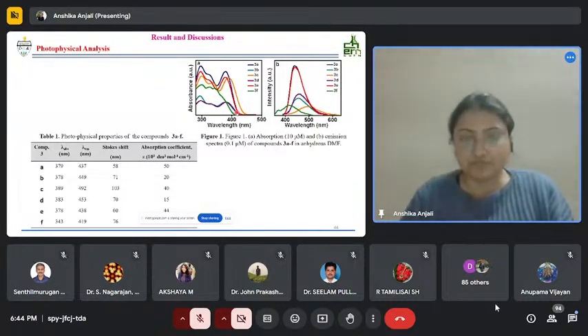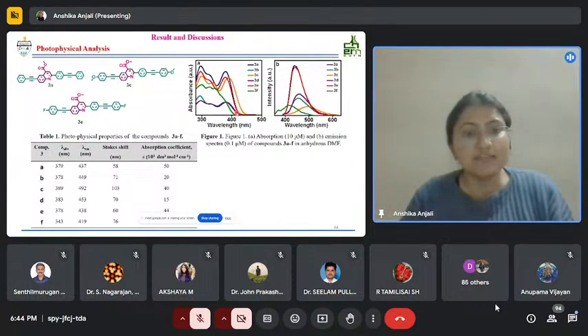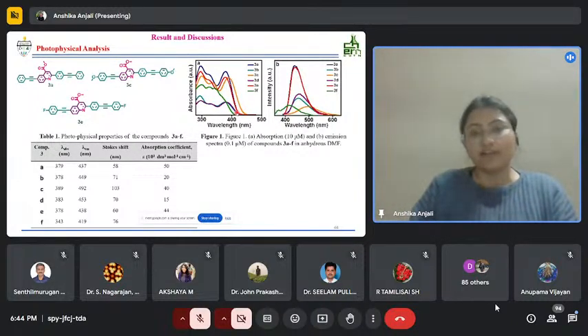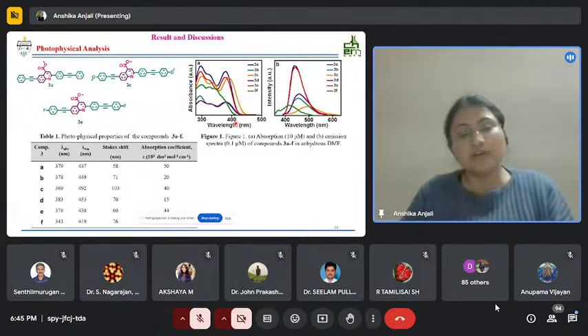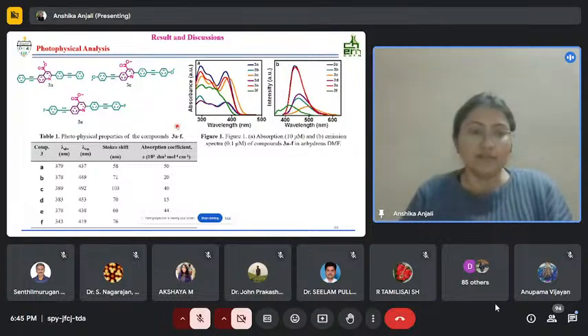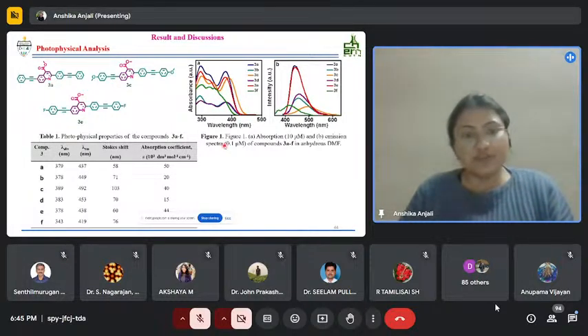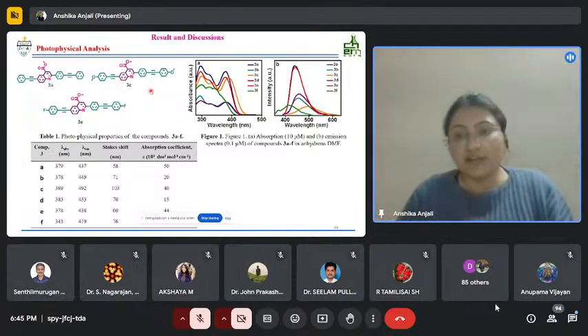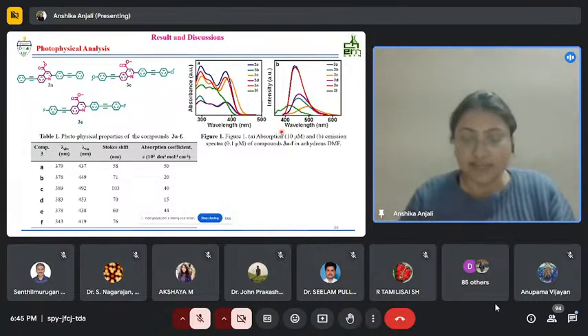So here compound 3A with the phenyl as end caps, then compound 3C with 4-methoxyphenyl as end caps, and compound 3E with 4-fluorophenyl as end caps resulted in higher ICT effect. So when we are comparing these compounds with the previous set of molecules with only one pi linker, they did exhibit a red shift, which might be because of the extended conjugation with additional phenyl as a pi linker here. We have observed a broad emission band for the compound 3F with this cyano functionalization. We have observed a blue shift in the absorption and emission spectra.